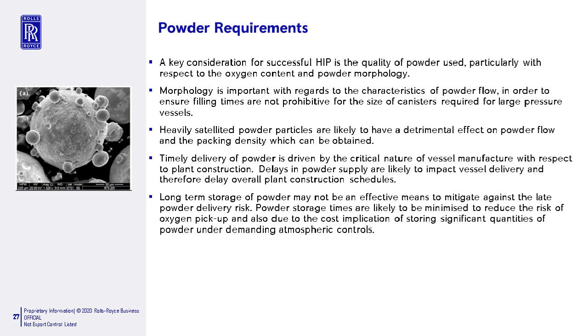We must avoid heavily satellited powder particles. So you can see on the left hand side there a number of little satellites around a particle of powder. They can cause the powder to be sticky and not flow freely, and then you can have issues with packing density, which downstream can give you an issue with the consolidation of your actual structure.